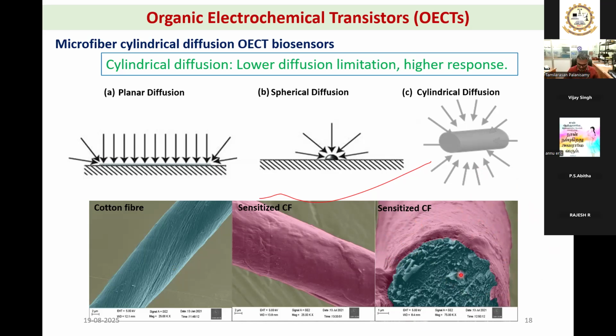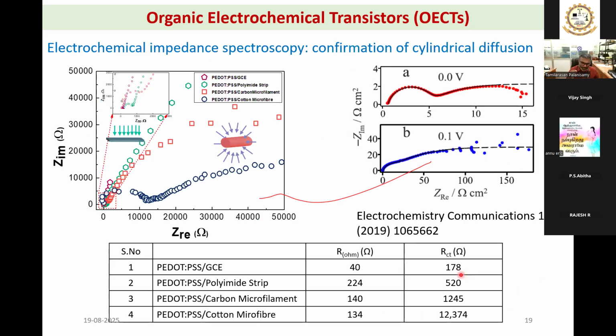Okay, and we attached the fiber on an OECT as a channel, and then we have demonstrated a sensor. And here we have claimed that it may have a cylindrical diffusion. But how to prove it? We took help from the impedance spectroscopy, because if you see the impedance, this is the charge transfer kinetic region, but the lower frequency or higher impedance region is your diffusion region. And in this region, the impedance depends purely on the type of diffusion, whether it is a planar diffusion or a spherical diffusion or cylindrical diffusion.